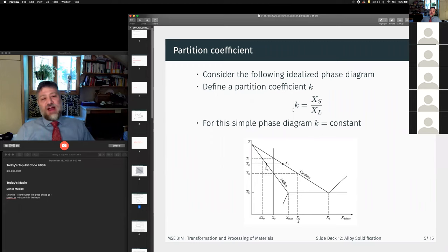Okay. So we want to define a pretty important parameter. And this parameter is important not so much for any real physical reason, but because it gives us a nice mathematical convenience. We're going to call this the partition coefficient. The partition coefficient is the ratio between the composition of the solid and the composition of the liquid. And when we have a phase diagram where the solidus and liquidus lines are straight, this becomes a constant. So if we don't have too much curvature here, this really simplifies the analysis for us, and we can make a lot of nice approximations if we do this.